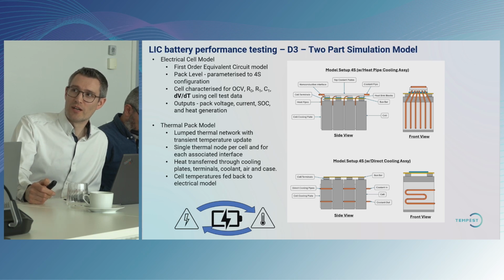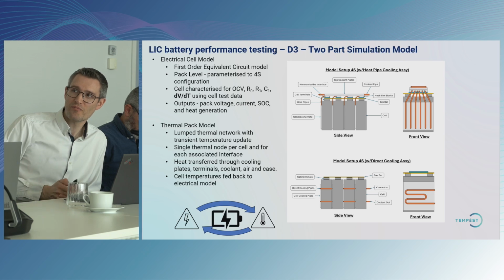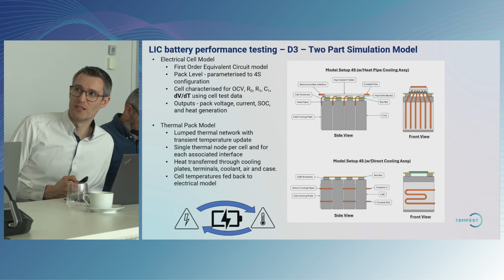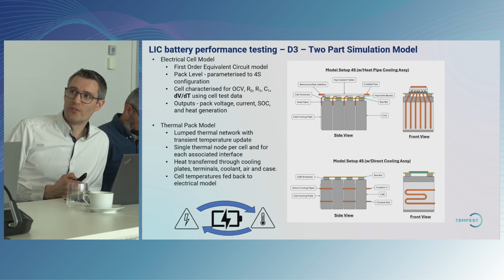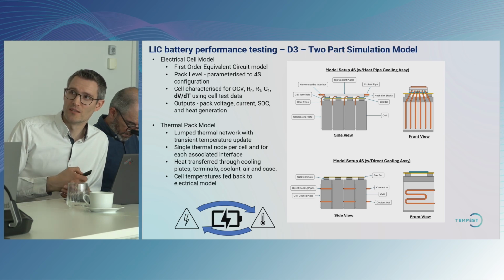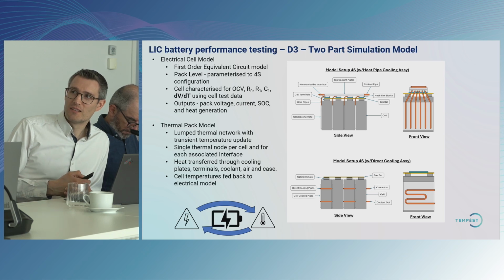Looking at the diagrams on the right-hand side, the one at the top is the one which we had experimentally. So we have heat pipe assemblies in between each of the cells, and they draw heat up to the heat pipe sinks at the top. We have 4 small aluminium blocks, which are the heat sinks of the heat pipes. Once the heat arrives at those heat sinks, it then needs to be evacuated to outside of the pack assembly, and that's the job of the top cooling plate. We have one top cooling plate for the group of 4 cells, and that's fed with water.